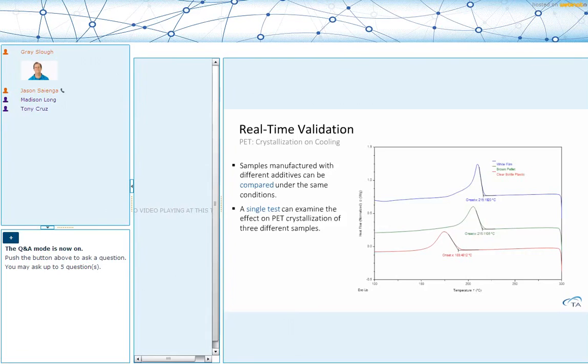You look at this particular example, we have PET crystallization on cooling. These are 3 different samples. Maybe they're different manufacturers, maybe they have different additives, maybe they have different nucleating agents. But clearly they have different crystallization peaks as we cool them down. A single test in this case can provide us information about how your material compares to a competitive material. So there's a reverse engineering aspect to it.